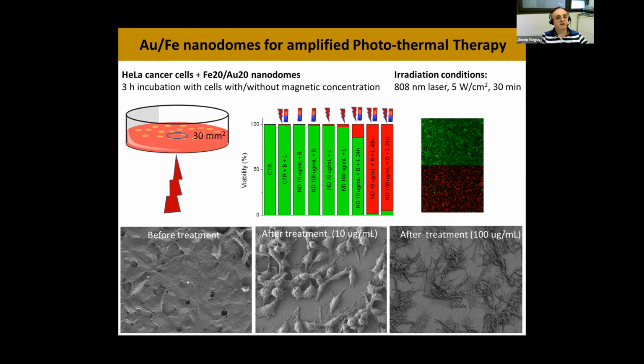We see before treatment they are nicely spread on the Petri dish, and when we use only 10 micrograms, you see that the cells have deformed, but they still look like cells. Meaning that here the cells are killed by apoptosis. However, when we do the treatment with 100 micrograms, we see that the cells are completely destroyed, like burned out. And meaning that in this case, we kill the cells by necrosis. This kind of cell killing is not appropriate because it leads to side effects.